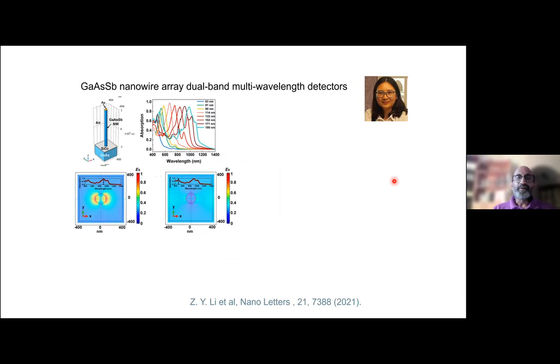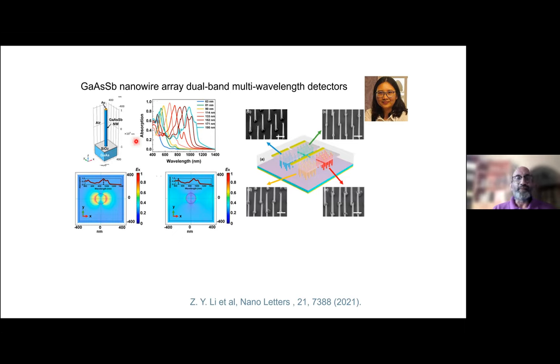So now let me finish off with this: can we use nanowires only for terahertz detectors, or for other detectors as well? In fact, we can use them for visible and infrared detectors as well. You can see that by changing the nanowire diameter, we can change the resonances of the absorption of these nanowires. As we change the diameter of the nanowire, you can see that the resonant peak changes to the infrared wavelength region from the visible region, for example. You can see the electric field distribution in these particular nanowires from the top view.